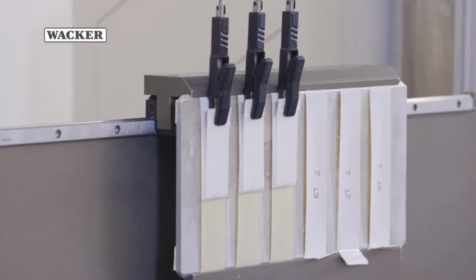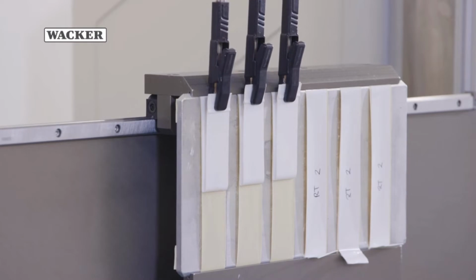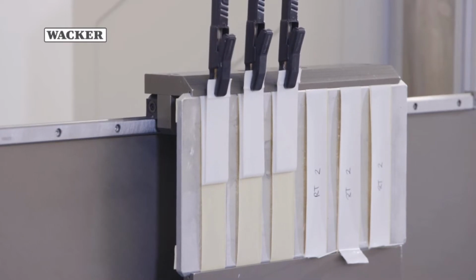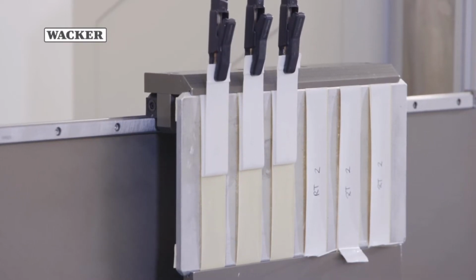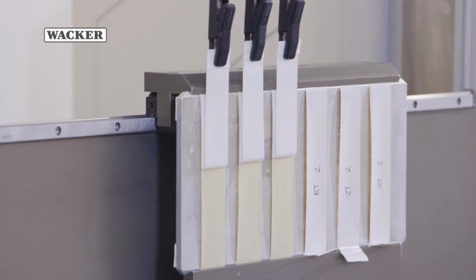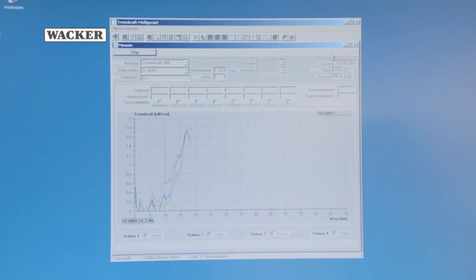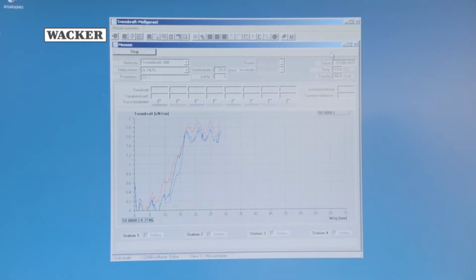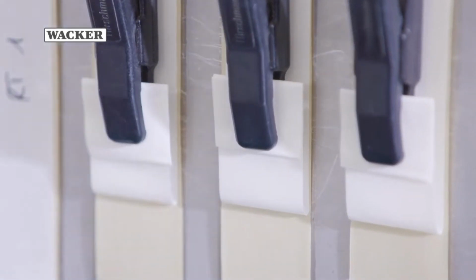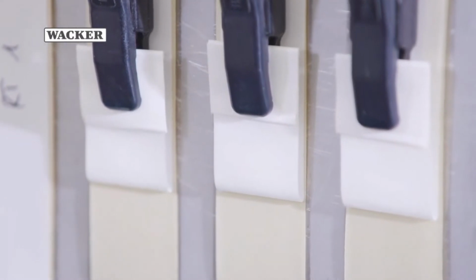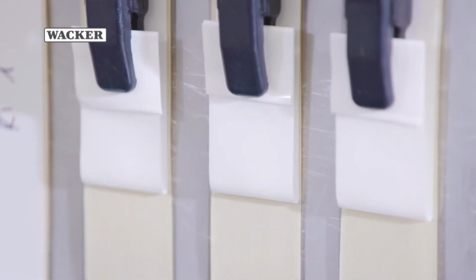In this test, at an angle of 180 degrees and a peel rate of 300 mm per minute, the label or adhesive strip is peeled off the release liner. During this test, the force is measured continuously. The average value for each test strip is calculated from the intermediate range. Each test is repeated with 3 identical strips and the mean is determined.